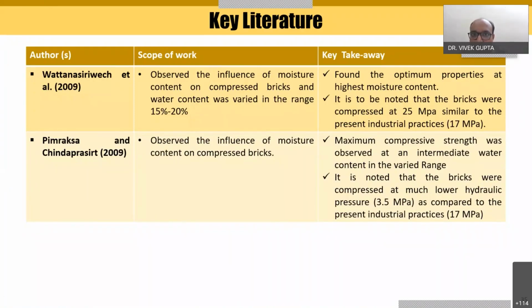I have put just these two literatures to show that there is no clarity on whether the moisture content should be at a maximum level or in an intermediate range, because the codes have not reported any clear-cut guidelines on how to select the moisture content while preparing the bricks. The manufacturing guidelines for bricks are still awaited from the researchers' side, but these are some of the areas where we have worked.